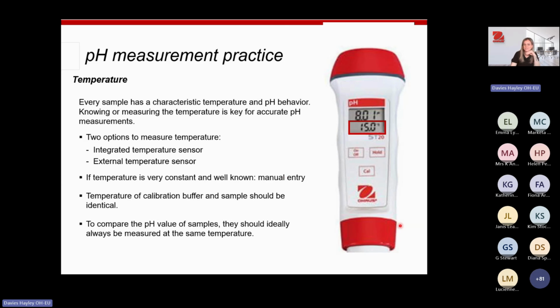Generally, they are set to around 25 degrees, but if it's anything different to that, you can manually enter the temperature into the meter, and it will use the built-in algorithm to determine what the pH is based on that temperature. If you've got an integrated temperature sensor, then that will work it all out for you. And you'll see on this one here, it has the temperature showing as well as the pH value. Again, make sure the temperature of your calibration buffer and your sample is identical, just to make sure they're measured at the same temperature.